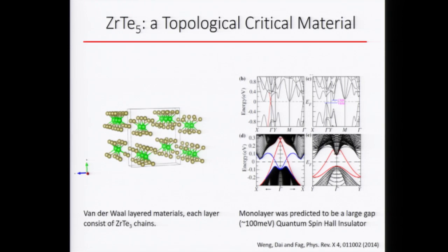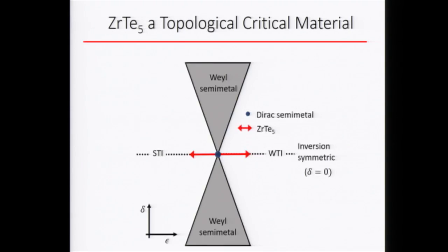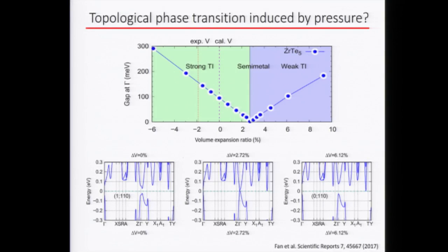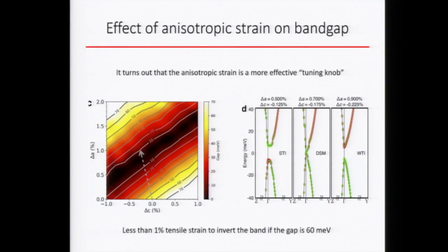Okay, so we're increasing the distance and we're improving the hopping by compacting. So you're decreasing both the interlayer constants and then the intralayer. Yeah. I actually cannot answer exactly which orbital is moving up or down to result in this, but the actual DFT calculation is showing that this is the best way to invert the bands.